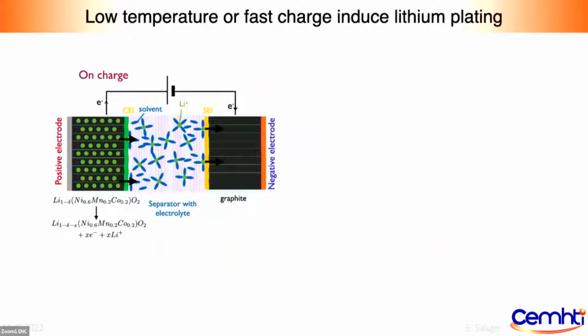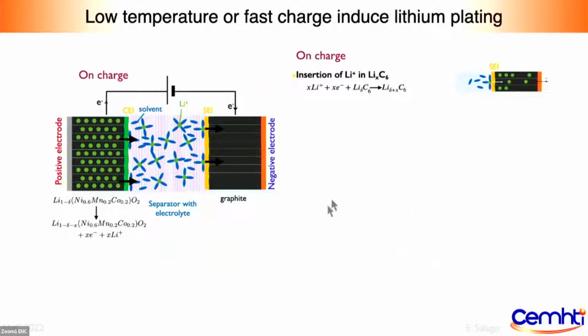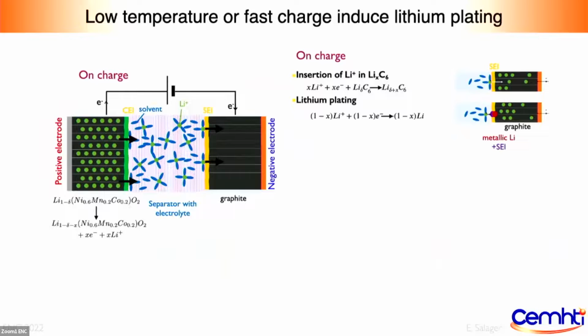So what happens is that at the negative electrode, we get reduction of the carbon by an insertion of lithium. This is the normal reaction that is highly reversible. And now, if you go really fast or really low temperature, you get overpotentials that make this reaction possible. That's the reduction of lithium ions. And it does plate on the surface, and that's an issue because it can have different microstructures or react with the solvents and consume lithium.